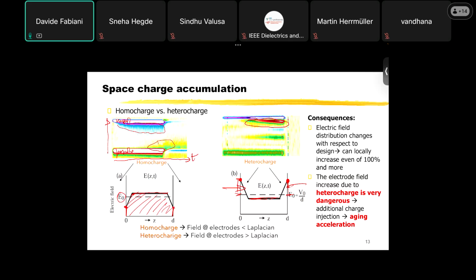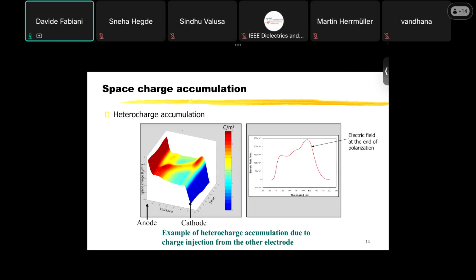And this is another example. You see here a 3D pattern where you see a packet of positive charge that during time moves and reaches the negative electrode, creating heterocharge. And as you can see here, the electric field close to the negative electrode becomes higher and higher. In that case, it is about 90% higher than the average field, that is this one. This is the average field, and this is the localized field close to the negative electrode, which is very, very high, as you can see here.